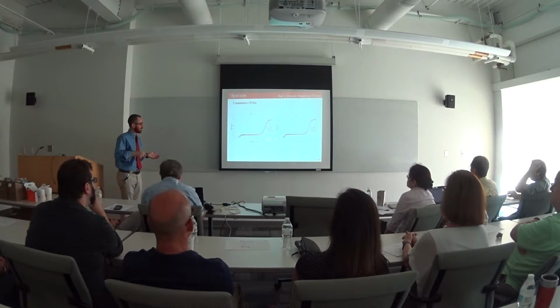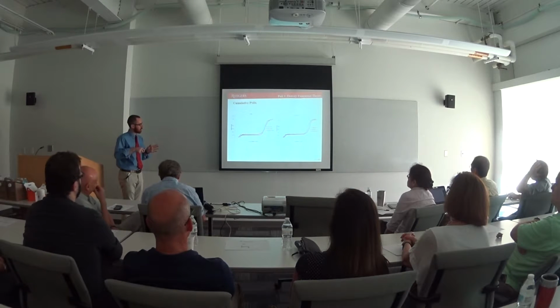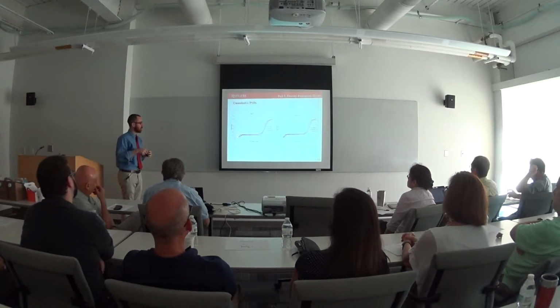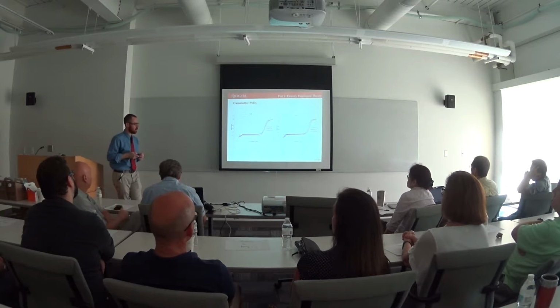Also, we can look at the cumulative pore size distribution. Along this axis we have the pore width, and this is the total volume at one pore width. As we progress along this graph, we're adding the total amount adsorbed at each step. So we have a first uptake that occurs in your micropores, and then the second uptake that occurs in your mesopores. And we have really excellent agreement across all the analysis gases for this.